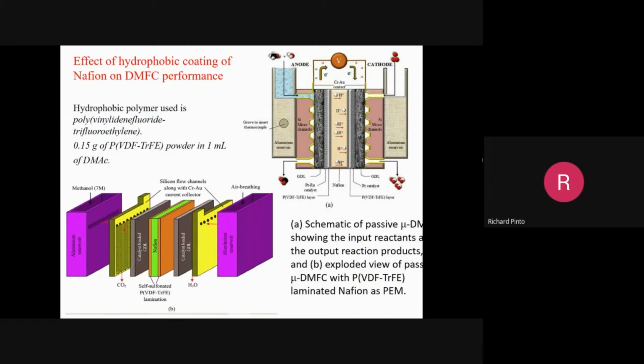But the relation to that is that PVDF-TrFE is one material which is piezoelectric, but it also helped us here in the direct methanol fuel cell work. What we did is we coated the membrane with PVDF-TrFE, just by spin coating, and then found this effect. You see the schematic here. Before I go into the detail, let me explain the schematic in one minute. Here is the self-sulfonated PVDF. Why self-sulfonated? I'll explain later on.